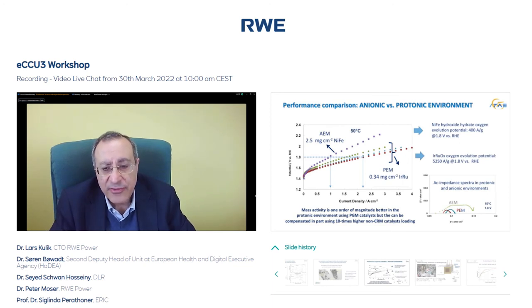And here in slide number 14, we can have a comparison of the performance of the electrocatalysts for the oxygen evolution reaction in the protonic environment and the anionic environment. You can see that even if we have reduced by 10 times the catalyst loading at the anode in the case of the PEM electrolysis cell, using iridium, ruthenium oxide, the precious metal electrocatalyst, we still have twice the current density at 1.8 volts operating cell voltage. And of course, there is a difference of one order of magnitude in catalyst loading, but the current density is much better in the case of precious metal electrocatalysis in the protonic environment.